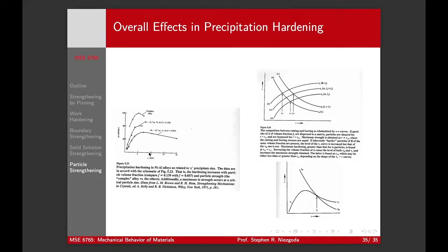So this is precipitate size, right? And this is hardening, right? There's a maximum size before it gets smaller, right? And this is due to a couple of things, right? Primarily, we see this as the particles get larger. If we stick at a constant volume fraction, the separation between them gets much larger, right? So our denominator, that L prime, gets larger, so our effect goes away.